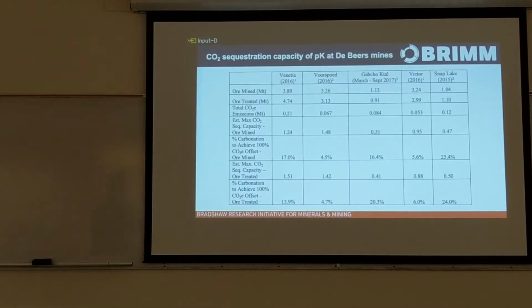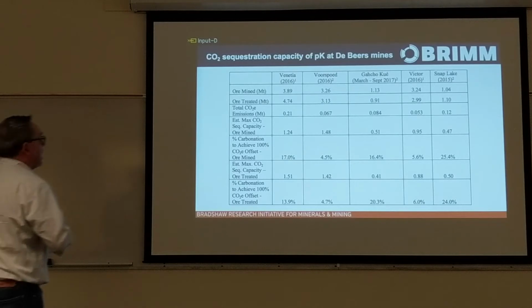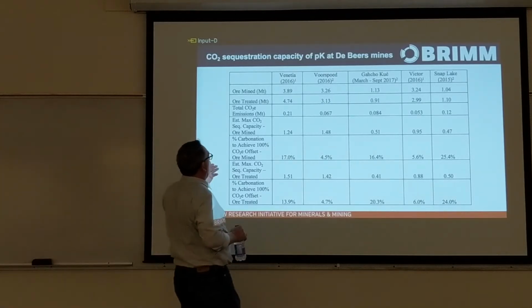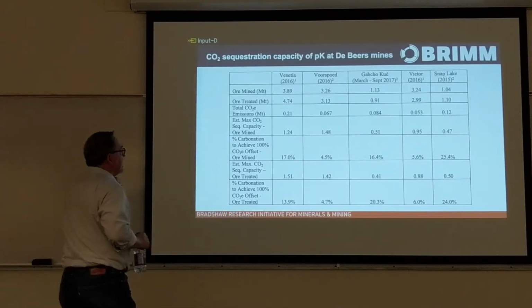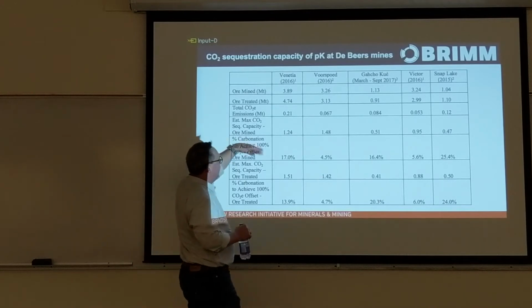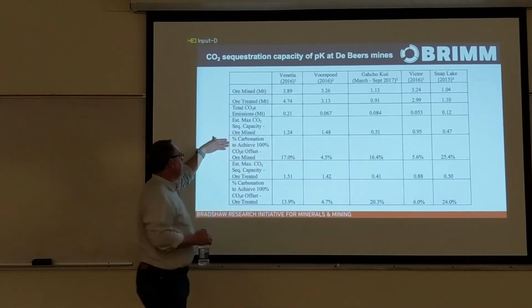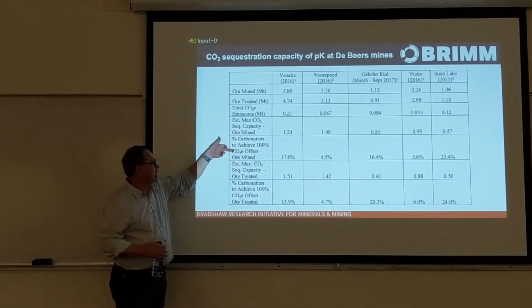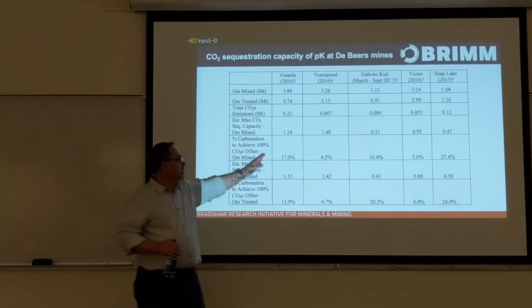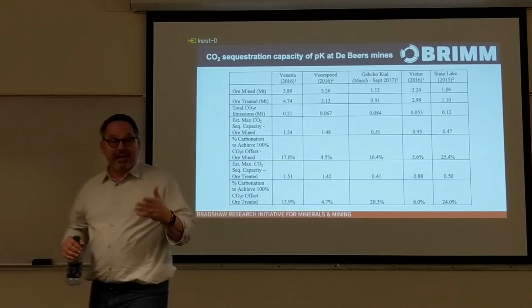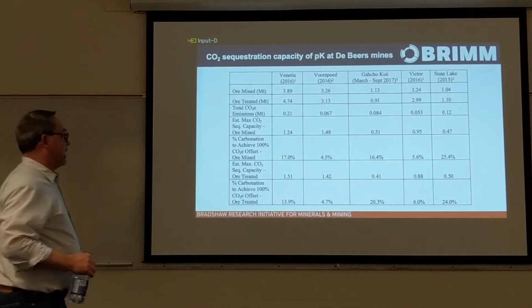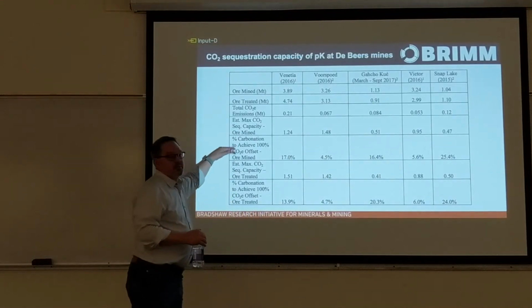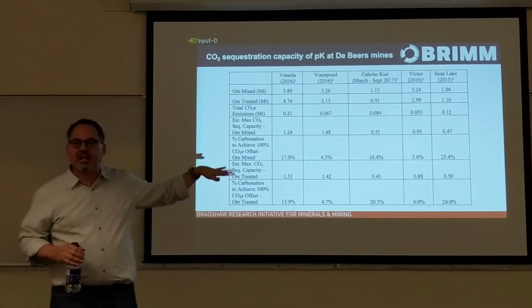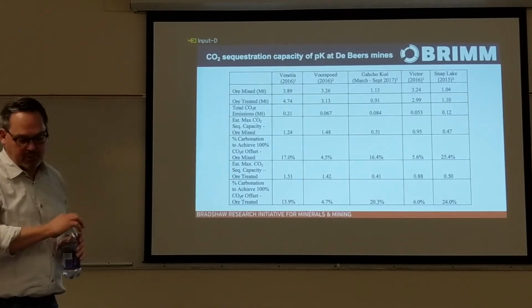So we've started doing similar studies for De Beers, looking at some of their different mines, and this is in a paper that came out of the last Kimberlite conference, essentially looking at how much material we would have to react to achieve essentially 100% offsets. Again, it's on the order of 10% of the material if you fully reacted it. This is not the labile magnesium content, this is the total magnesium content. But this is just to illustrate that Kimberlite has these same properties.